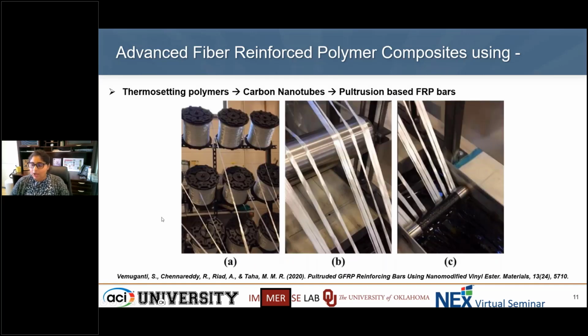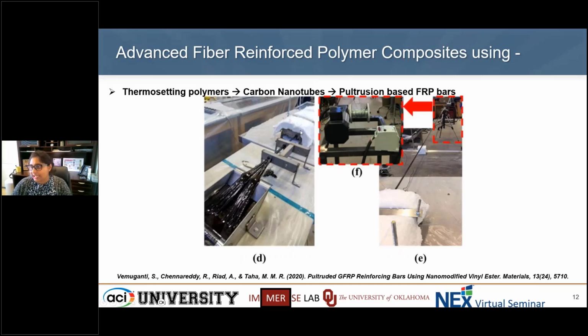This is more of an on-site picture that you can see. We have glass fiber rovings that are being pulled and tensioned into this vinyl ester resin bath. The resin itself is translucent, but because of the carbon nanotubes added, you see more of a dark color. Once the glass fiber strands are pulled into this resin bath, we have a preformed die which is heated, and the strands are pulled out, formed into this number 3 bar cross section, and a pulley is basically pulling those bars out. So in this kind of method, we were able to actually alter that polymer matrix that is used to make pultruded bars.